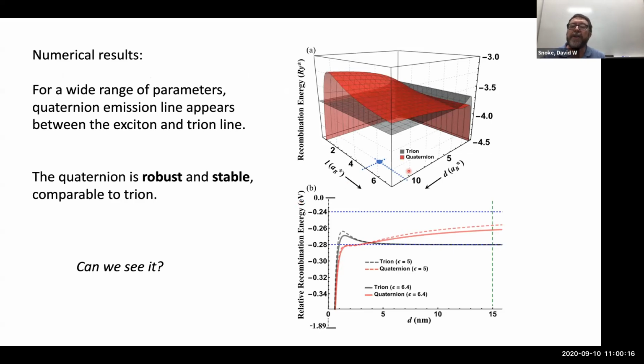So if you look at this figure here, this is D, the distance to the metal, and this is L, the spacing between the 2 monolayers. And then you can see the quaternion recombination energy is this sheet here, and the trion is here. And so for a wide range of energies, the quaternion sits above the trion in its photoemission energy and below the exciton energy. And so now you see here just a slice where we've picked a specific L, and now we're putting actual units on this.